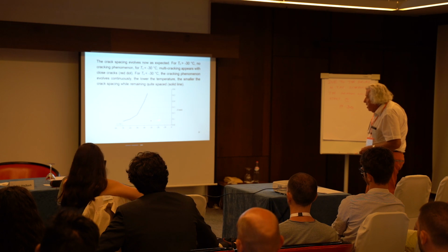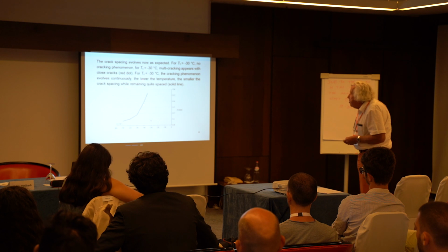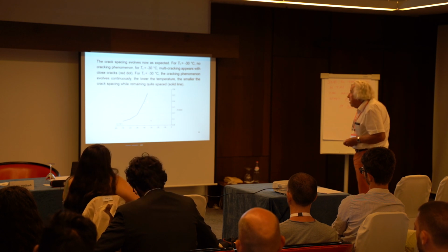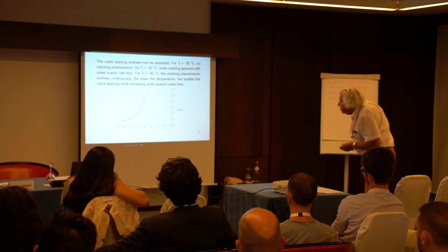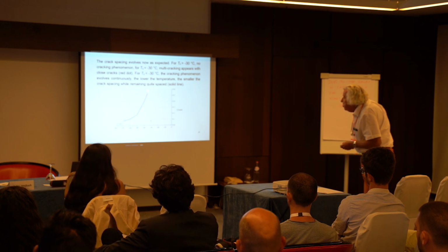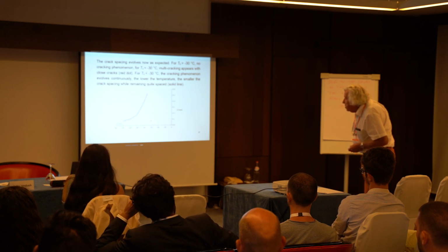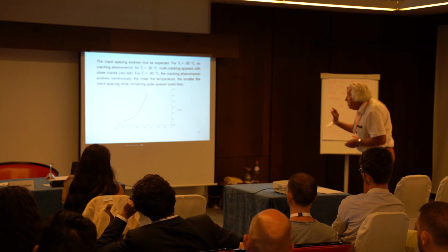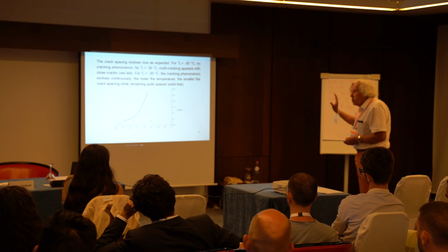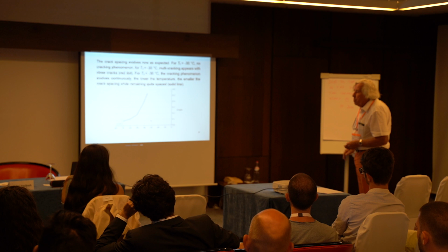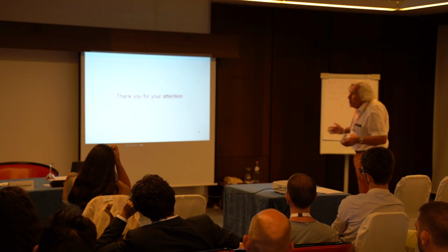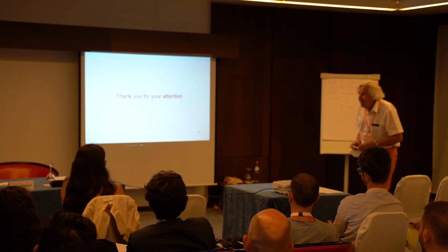The cracks are close to each other here, and then if we try to do calculations for lower temperatures, for instance minus 35, minus 40, you see that at minus 30 degrees Celsius you have very close cracks, but next you have a larger crack pattern, of course, that slowly increases when the temperature is lower and lower. So I think that we have solved the paradox.